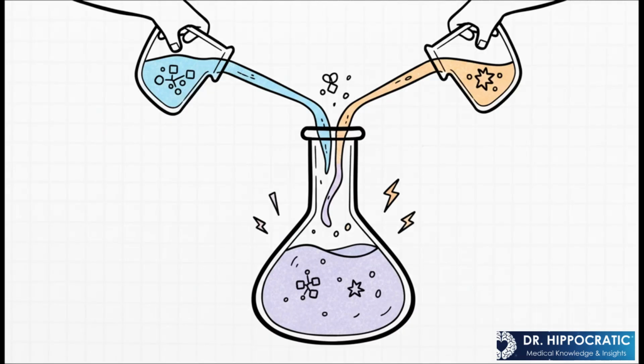All right, onto the liquid. This is where the EBA in the name actually comes from. It's got ortho-ethoxybenzoic acid, we'll just call it EBA, and our old friend eugenol. Both of these are the active ingredients that are going to get that setting reaction started. Usually you're looking at a ratio of about 2 parts EBA to 1 part eugenol.